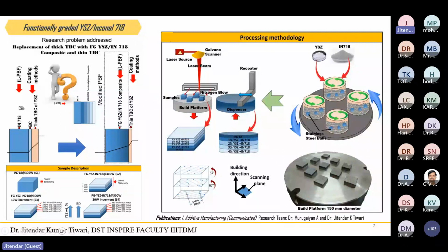So okay, let's come to this idea that we can replace this whole system with the functionally graded material. We can take here Inconel 718, we can take other Inconel series, 625 or anything. We can try, maybe in future it is open to all, and a thin TBC of YSZ. So once you get the functionally graded YSZ, only a thin TBC will be required, and there are chances that obviously after a long duration of application there might be cracking, but here the chances will be lesser, because the coating is thin. In general, the thickness of the coating is around 1000 micron or 1 mm, if we are targeting a larger thickness coating, but usually it can be 500 micron or 600 micron in that case.